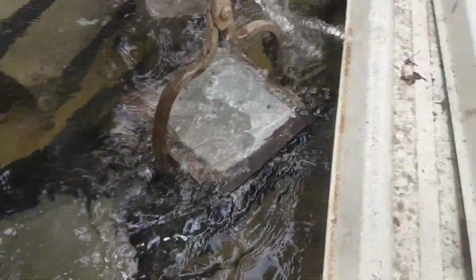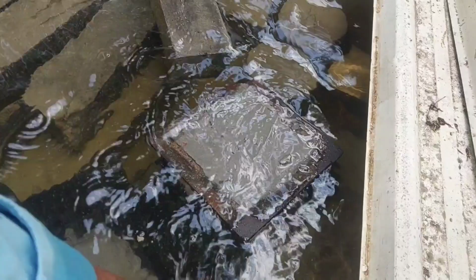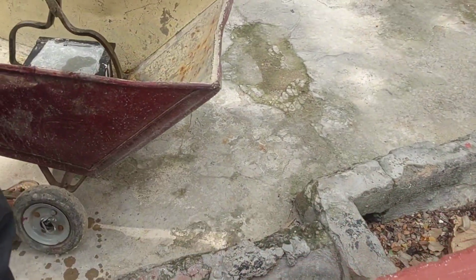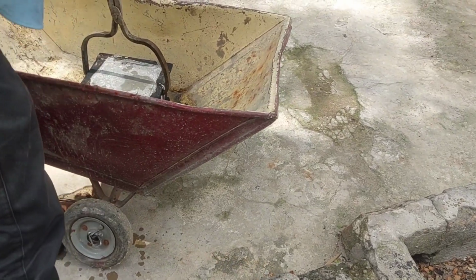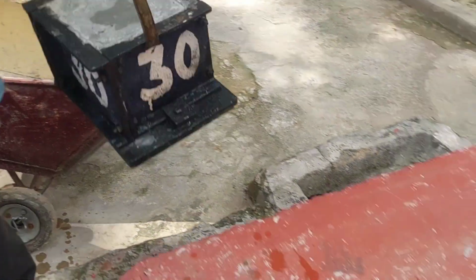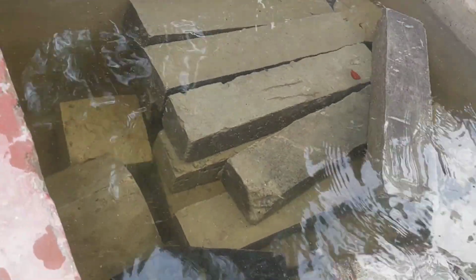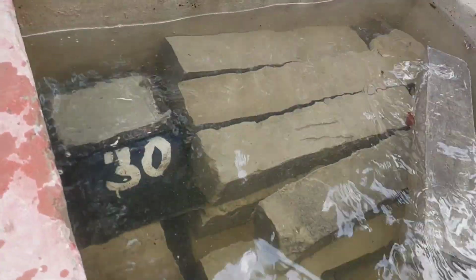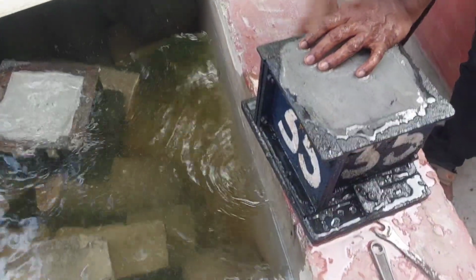And now you can see the concrete cubes are placed in a normal curing tank to know the compressive strength of the concrete after removing these cubes from the curing tank at about 1 hour. Then the cubes are tested for compressive strength using a compression testing machine. The data should be recorded and analyzed to estimate the 28-day strength of the concrete. So this is how we know the procedure for the accelerated curing tank.